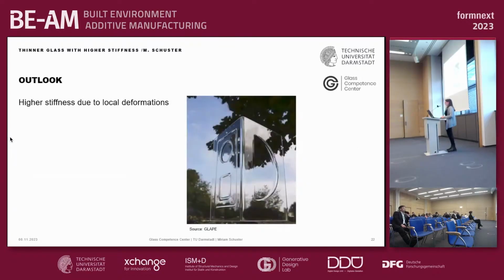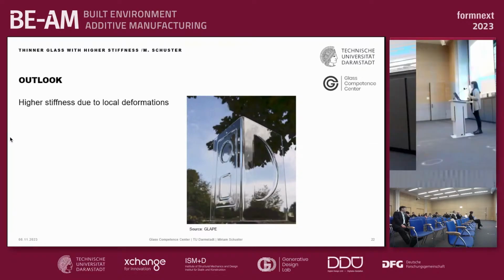Then there's another thing I want to present to you very briefly. I have talked about that the biggest advantage of AM in the glass field could be to print some reinforcements. And instead of printing reinforcements, we are also looking at local deformations of glass and stiffening it in that way. And here I have a sample where the glass was locally deformed, and here we have then a linear reinforcement. And this is even less material, so maybe also a very, very good option in order to reduce the glass thickness.